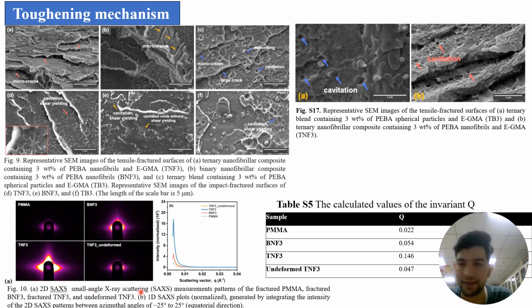it is the SAXS, small angle X-ray scattering pattern. A fractured sample shows higher crazing. It shows that the crazing is very high in TNF3 compared to PMMA, BNF3 and undeformed TNF3. So this suggests that TNF3's higher toughness is due to more craze initiation and controlled growth. The presence of EGMA at the matrix-nanofiber interface initiates more crazes and controls their growth, resulting in uniform crazing across the matrix.